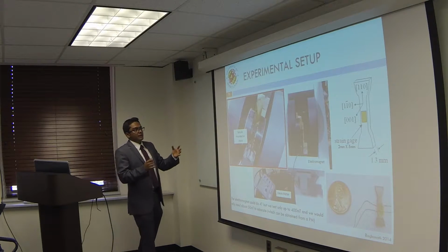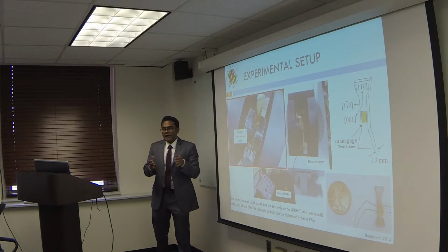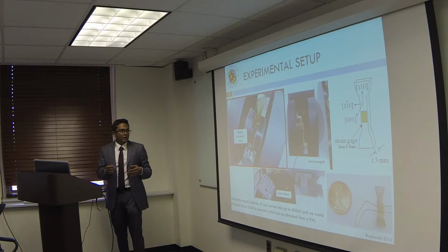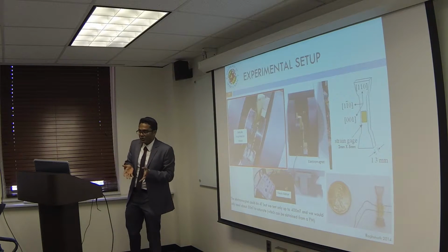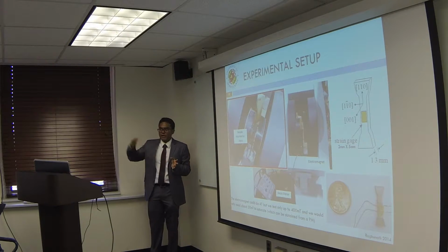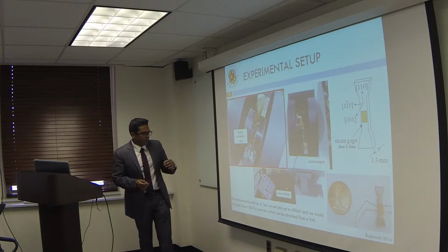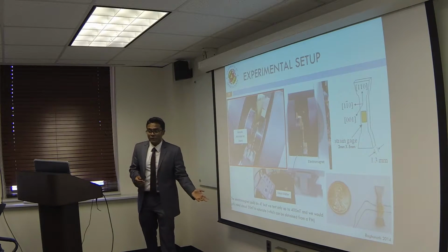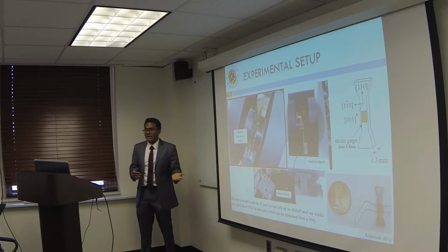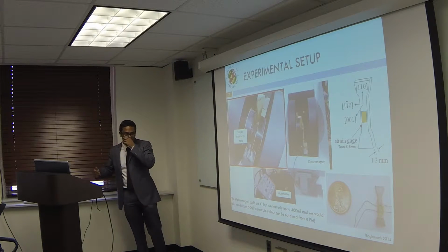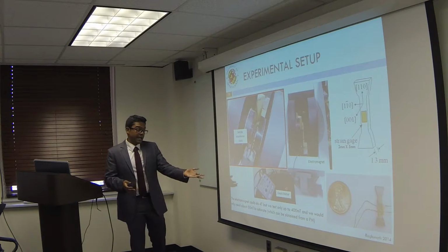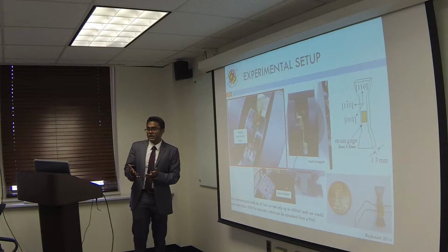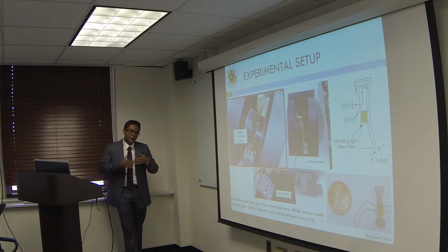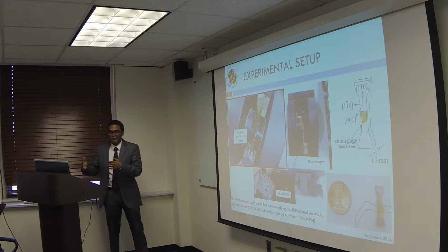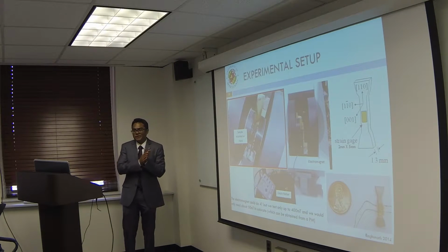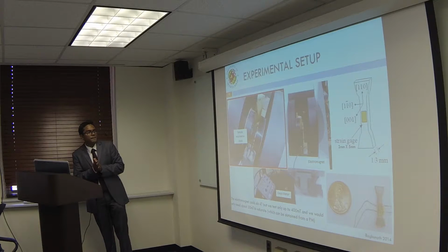The samples were mounted between the pole pieces of a bias magnet using double-sided tape. We had a feedback loop control to control the magnetic field as we ramped up and ramped down. Although the magnet could do up to 4 Tesla, we only needed about 50 millitesla to saturate all our samples, as in take the samples to magnetic saturation. This can actually be obtained even by just using a permanent magnet. The other reason why we didn't want to go past 400 millitesla was we were afraid that the pole pieces might rip the sample away from the stand.